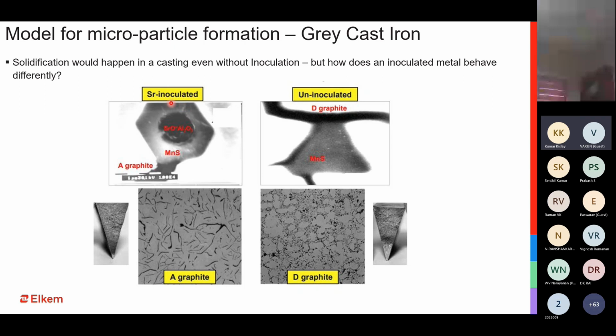Of course, when you have this kind of a surface, when you have this kind of a structure, the kind of microstructure that you get would be more of a type A, random distribution, a much better graphite flake distribution, much better control on the flake thickness, the length of the flake, and a random distribution would make sure that your casting achieves all the mechanical properties and the thermal properties that it is supposed to achieve. Plus, if you also look at the wedge, which is corresponding to this kind of a microstructure, you have minimum carbide, so minimum chill.